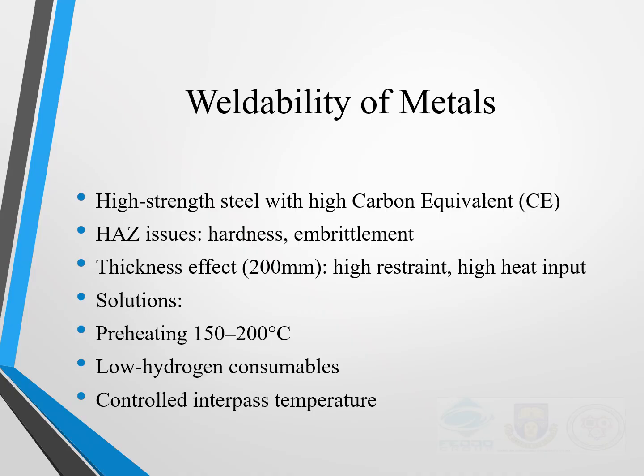The pad eye was made from a high-strength steel. Such steels usually have a high carbon equivalent, which makes them prone to cracking. The heat-affected zone, or HAZ, can become very hard and brittle if heat is not controlled. The 200mm thickness also means higher restraint and high heat input, which increases risk. To improve weldability, I recommended preheating between 150 and 200 degrees using low hydrogen consumables and controlling interpass temperature.